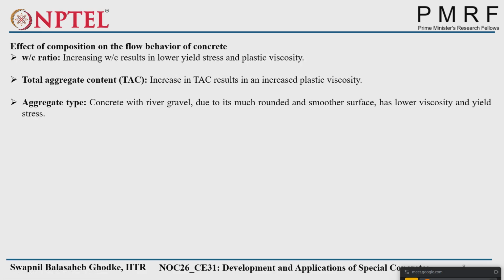So apart from that, what are the different factors affecting the water to cement ratio? Increasing the water to cement ratio results in a lower yield stress and plastic viscosity. We saw that because of the dispersion of the particles, trapped water gets released, which is responsible for increasing the flow, and at the same time, due to the increased flow, yield stress and plastic viscosity decrease. Second, total aggregate content. Increasing total aggregate content results in an increasing plastic viscosity. Can anyone tell me how it is possible that increasing aggregate content increases the plastic viscosity?